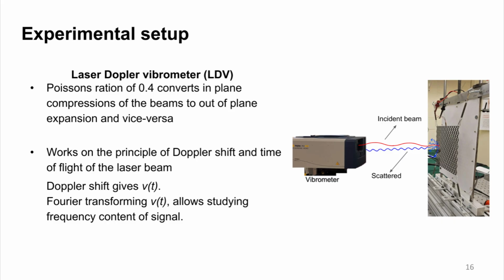My experimental setup also includes a laser Doppler vibrometer, and it works on the principle of Doppler shift. Doppler shift measures the frequency change if an object is moving relative to the laser Doppler vibrometer, and that gives me V of t data for a continuous scan. V of t data can be Fourier transformed, and in the Fourier domain I get V tilde of f as a function of frequency, and that allows me to examine the frequency content of the vibrations in the metamaterial.